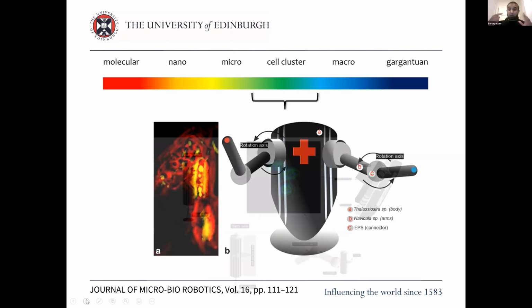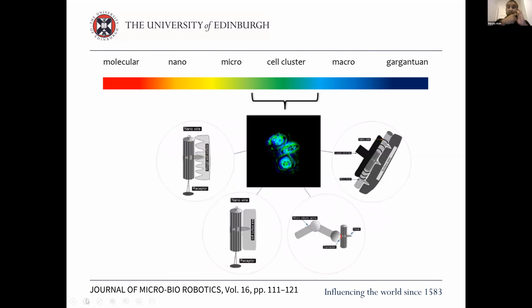There are other diatoms, pennate ones, that will actually enter into cylindrical diatoms, and then you'll have a glass-glass interaction, whereas the previous image you saw was glass, biopolymer, glass, biopolymer. So you've got soft, hard like that. Sorry, hard, soft, hard, soft. Whereas in this case, you've got hard, glass against glass. So it's something very rigid, but with a shape that is atypical of ordinary diatoms. And these kinds of things could also potentially be used in microbio robots. This is, again, preliminary work.